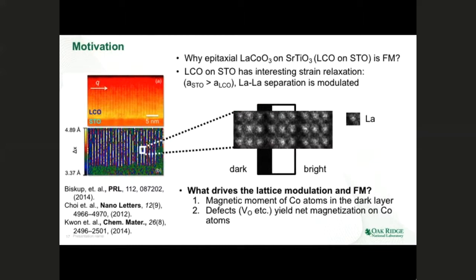When people grow these structures, they see this type of lattice modulation. If you look at the STM pictures closely, you can see that this feature is more prominent in these structures, where you have basically one dark layer and two bright layers, and the brightness is associated with lanthanum atoms. There are two physical reasons why ferromagnetism might occur in these systems. One would be that in the darker layers we see larger lanthanum separations, and that leads the cobalt atoms to obtain larger magnetic moments, which would drive the ferromagnetism in these structures.